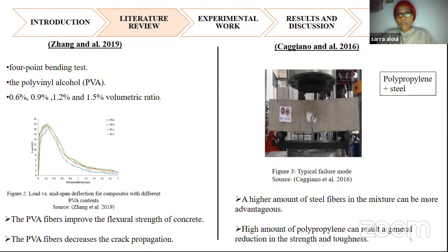The second one was done by Caggiano in 2016, where a high amount of steel fibers in the mix was concluded to be more advantageous, as well as we could conclude that a high amount of polypropylene can result in a general reduction in strength and toughness.